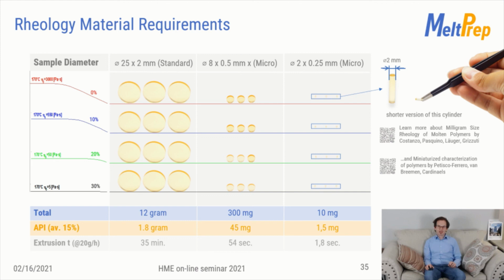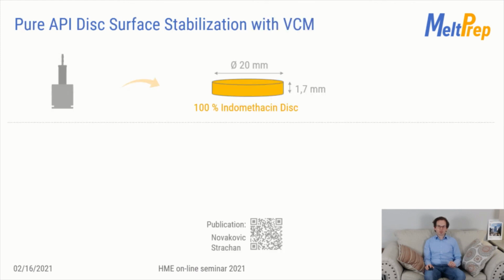Let's move on. This study was conducted by the group of Claire Strachan in Finland. This example is research to reduce the risk of surface nucleation of pure APIs. The starting point is a 20 mm VCM disk out of 100% API, in this case Indomethacin, with a height of 1.7 mm. Air humidity is causing stability issues, and the VCM samples immediately show surface recrystallization.